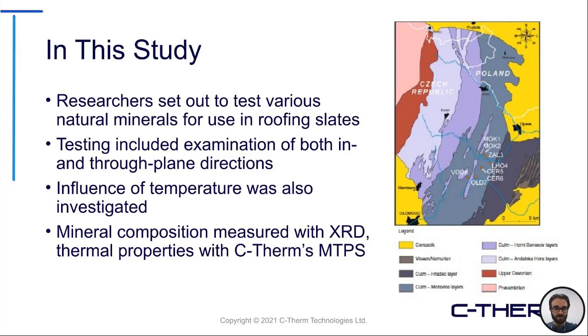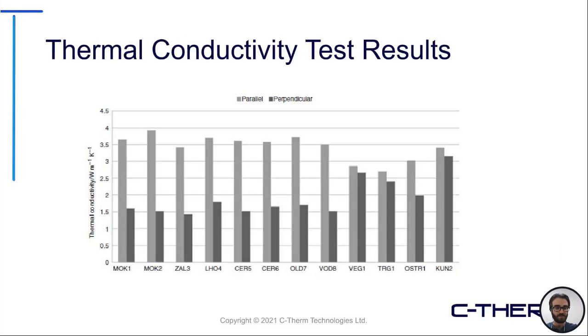Some more notes from the study that was done. The mineral composition for each thing that would be referenced is measured by XRD, but the thermal properties were all measured using C-Therm's MTPS sensor. So you can see here from the thermal conductivity results, they noted both the parallel or in-plane and perpendicular through-plane directions. And across all the various mineral sources that were taken, we did see, generally speaking, the parallel or the in-plane did result in a higher thermal conductivity measurement compared to that through-plane direction.